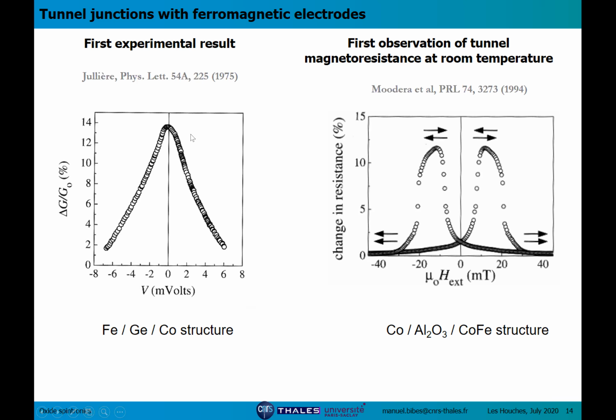And the curve here is the first curve that indicates a possible tunnel magnetoresistance effect. It shows the difference in the conductance between zero magnetic field and high magnetic field, normalized by, I think, the zero magnetic field value. You see that at zero or low bias voltage, this difference is about 14% and decreases strongly as voltage increases. So this can be taken as a first indication of tunnel magnetoresistance, but it's not very conclusive.